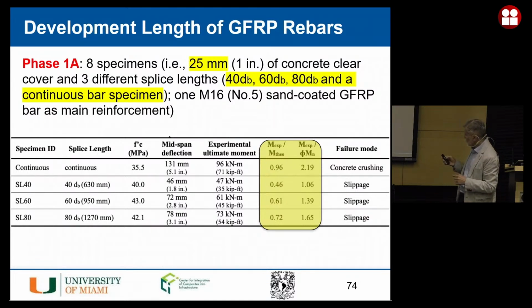And so look at this, these ratios. If you look at the experimental, this is using the material property tested in the laboratory, and you come up with a prediction. And obviously, if you have the continuous, you match exactly what you have. And then in the other cases, you are at 46, 61, 72%.